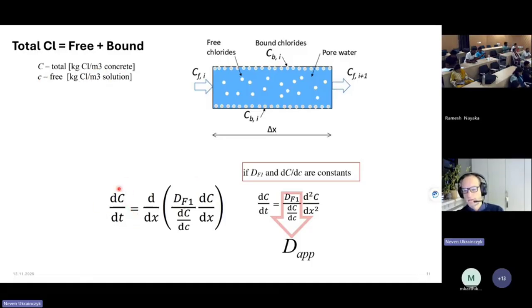We can derive the second Fick law. It basically means that the flux that comes in is equal to the flux that goes out. This is the flux, and this is the change of the flux in this direction. So what comes in must go out, because there is no reaction. If you would have a reaction, you just have to add a reaction. But if it's in steady state, what comes in must go out. So if there is no accumulation, this is zero. Then you have this Laplace equation, which is basically the second derivative of the concentration.